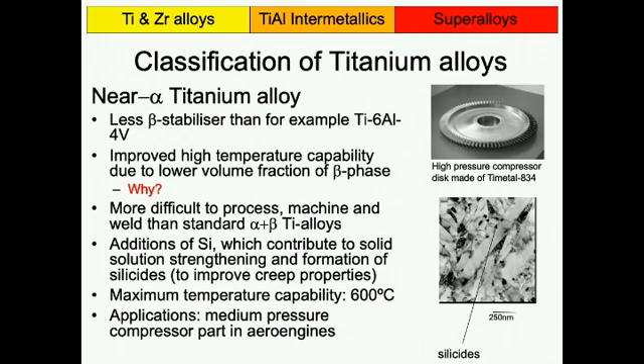They also tend to have additions of silicon, and silicon is added here to provide additional solid solution strengthening. It seems to pin dislocations quite effectively. And they also form silicides, and you can see here some TEM images of a relatively fine microstructure. In this case, it's also Ti-Metal 834, and you can see these black precipitates here. These are silicides, and they tend to sit on the grain boundaries. So they strengthen the grain boundaries, and it's believed to have a further contribution to improving the creep strength.